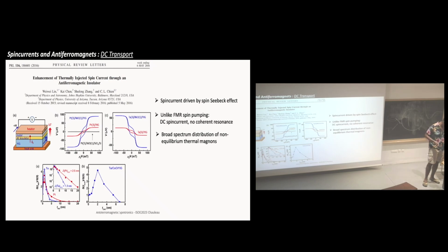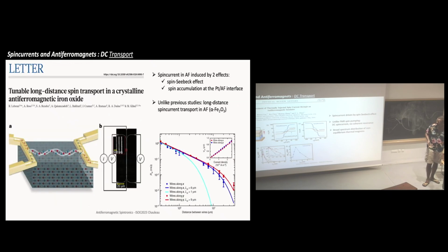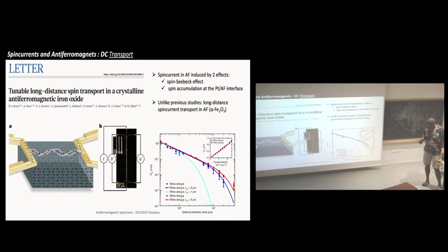But now we come, I would say, maybe to one of the major breakthroughs. We come to this paper, actually, which has been done by Romain Lebrun in the group of Mathias Kläui. And this time, they no longer use a thin layer, but a crystal of hematite, which is Fe2O3, also a well-known insulating antiferromagnet. And they put two contacts of platinum, and one is basically triggering the spin current, and the other one, exactly like the previous study, acts as a detector by spin Hall effect.